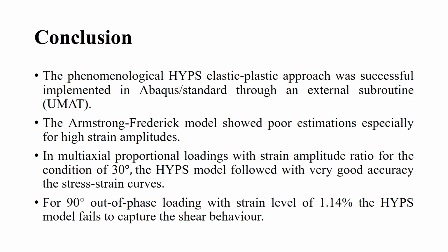The phenomenological HYPS elastic-plastic approach was successfully implemented in Abaqus. The Armstrong-Frederick model showed poor estimations, especially for high strain amplitudes. In multiaxial proportional loadings with strain amplitude ratio for the condition of 30 degrees, the HYPS model followed the stress-strain curves with very good accuracy. For 90 degree out-of-phase loading with the strain level of 1.14%, the HYPS model fails to capture the shear behavior.